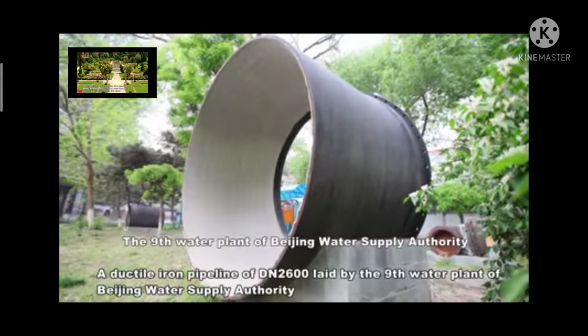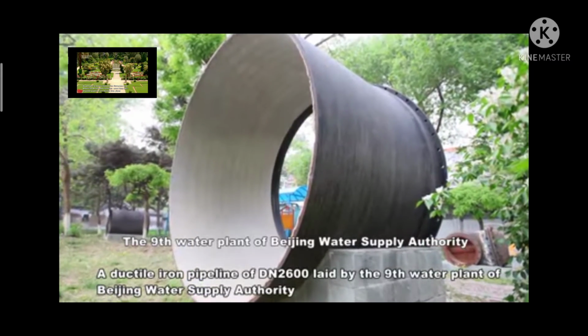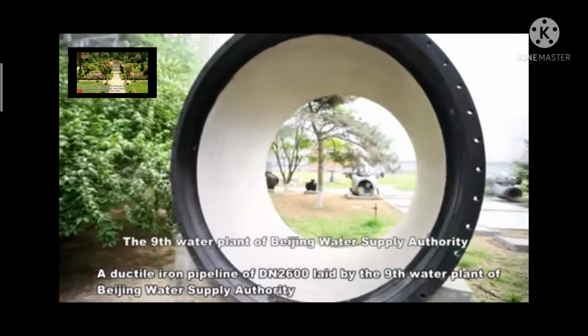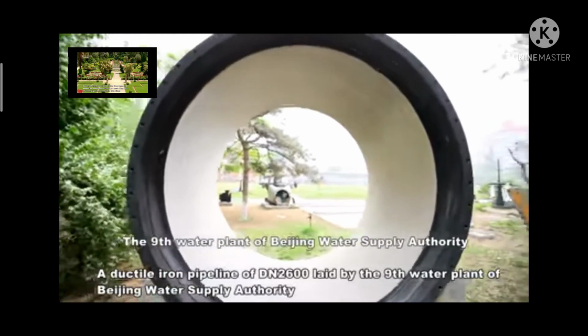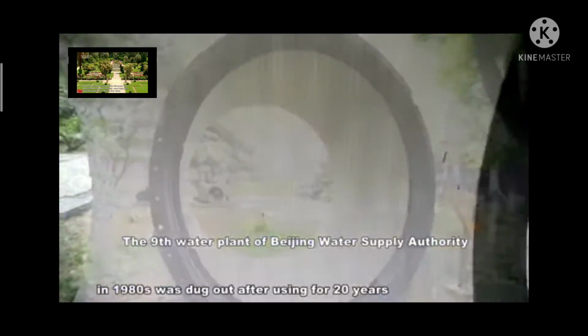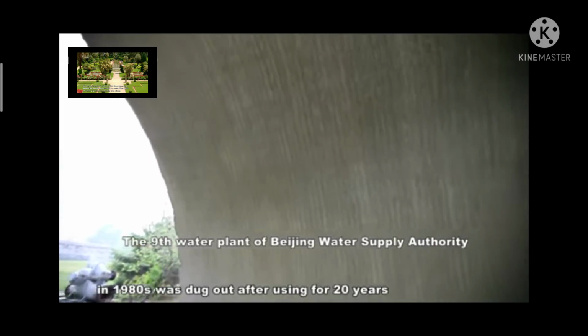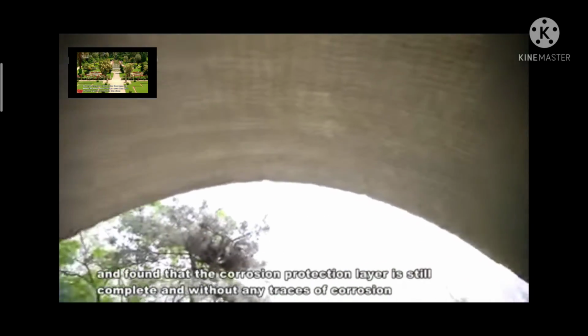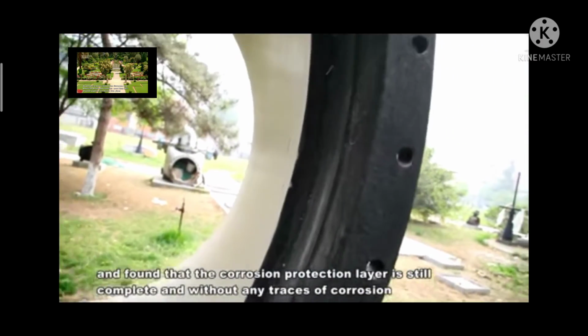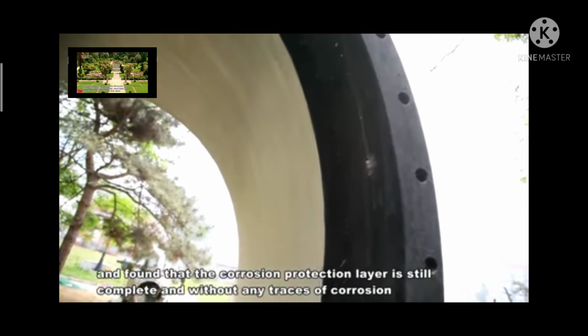A ductile iron pipeline of DN2600, laid by the 9th water plant of Beijing Water Supply Authority in the 1980s, was dug out after 20 years of use, and it was found that the corrosion protection layer is still complete and without any traces of corrosion.